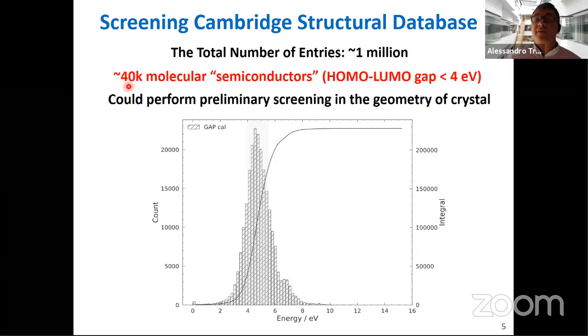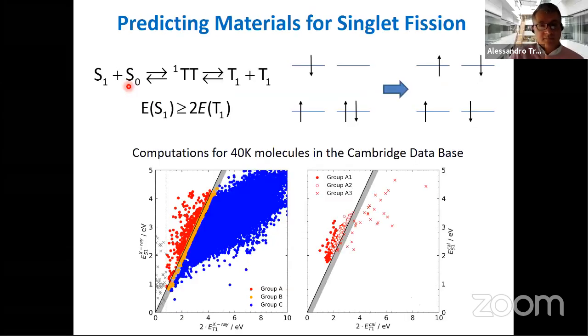So once we have 40,000 molecules that we identify to be interesting, so conjugated, you can excite them with visible or near UV light. We look for molecules with suitable energy levels so that they could undergo singlet fission. And so we computed the energy of the triplet and the energy of the singlet. Here we report double the energy of the triplet. And so all molecules which have an energy of the singlet slightly larger than double the energy of the triplet are potential candidates for singlet fission. Those are based on the crystal structure geometry of the molecule.